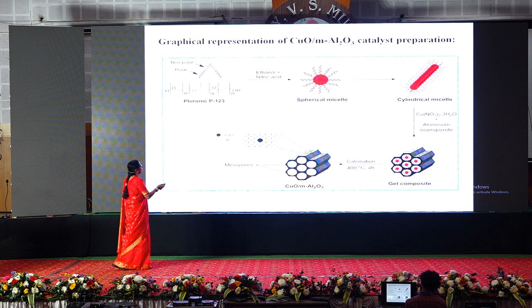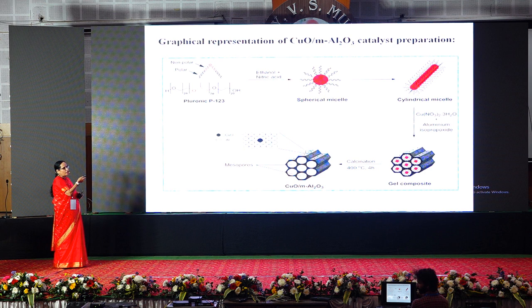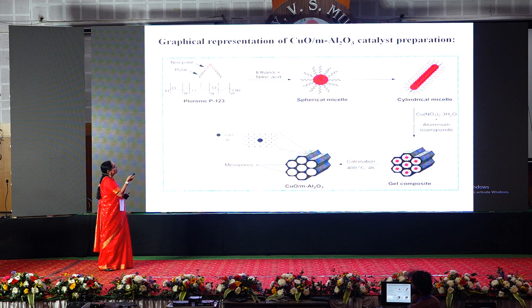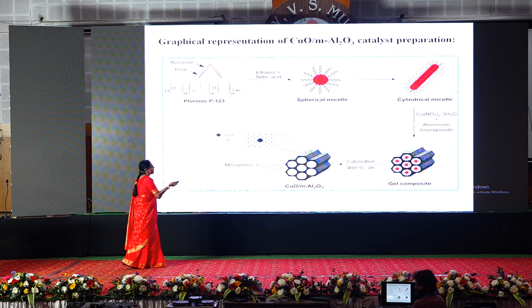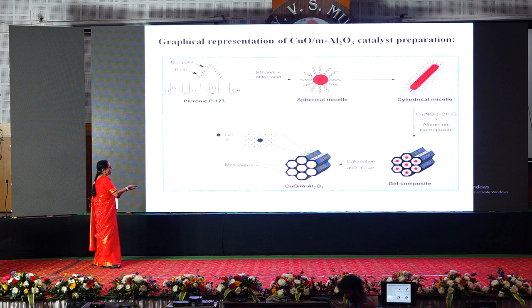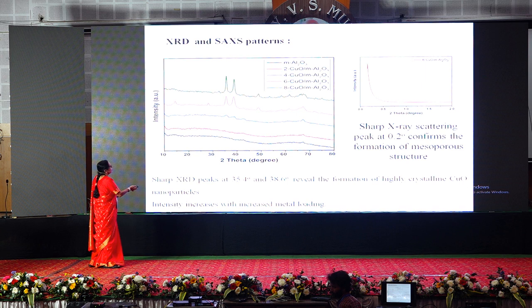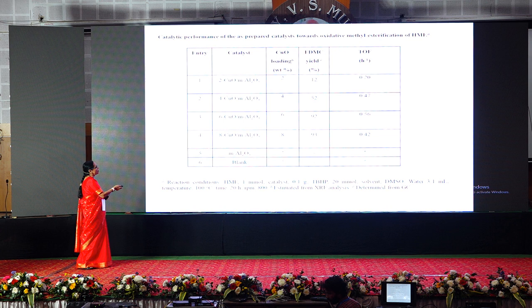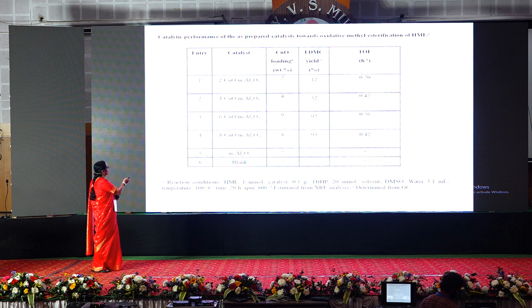You can take the Pluronic P123 and react with ethanol, nitric acid, copper nitrate, aluminum isopropoxide, gel, composite, calcination, and you will get the mesoporous alumina embedded with the copper oxide nanoparticles. And this one also we have completely characterized. You can see all the catalysts are very well characterized, and you can increase the copper percentage, you can see 8%, 6% copper, and you will get the FDMC, furan dimethyl carboxylate, in very good yields.